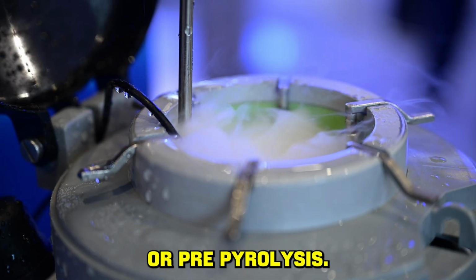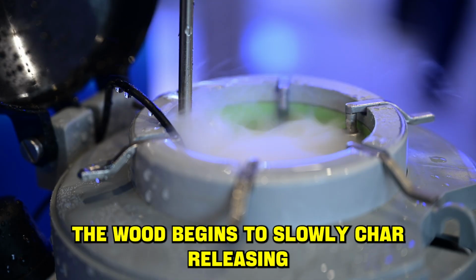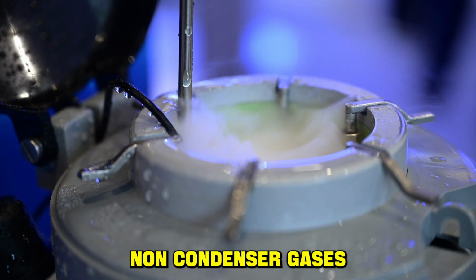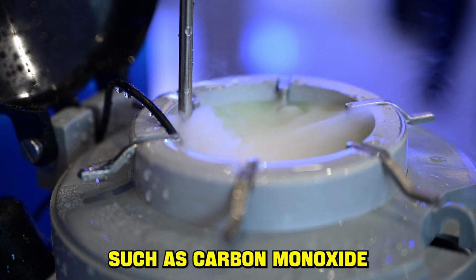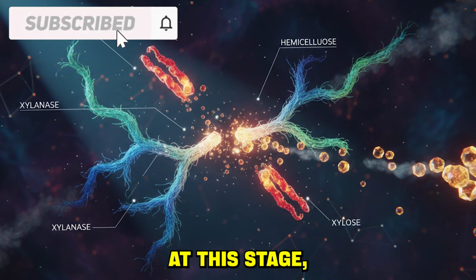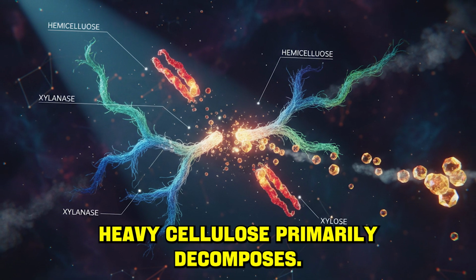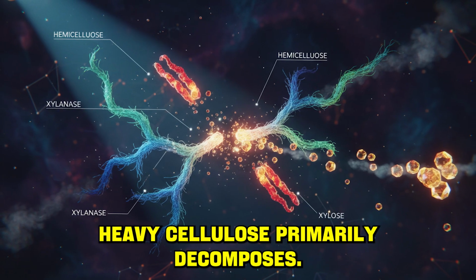The second stage, beginning at 150 to 200 degrees C and lasting up to 280 degrees C, is endothermic decomposition, or pre-pyrolysis. The wood begins to slowly char, releasing non-condensable gases such as carbon monoxide and carbon dioxide, as well as acetic acid and methanol vapors. At this stage, the least thermally stable component, hemicellulose, primarily decomposes.